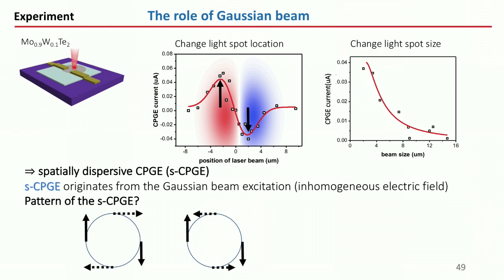So we took the laser and scanned across the bisector of the two electrodes. When we are far away, there is no response. Then as we start approaching the electrode, the response increases. Then at the intersection of the two electrodes, because it's a high symmetry point, the response goes away, and then it flips the sign. So something very interesting is happening. Another interesting thing was, if we keep the laser excitation spot fixed but change the laser spot size, then when the spot size is very small, the response is strong. And as the spot size becomes big, which means in the homogeneous excitation limit, where the spot is much bigger than the size of the sample, the response goes away.